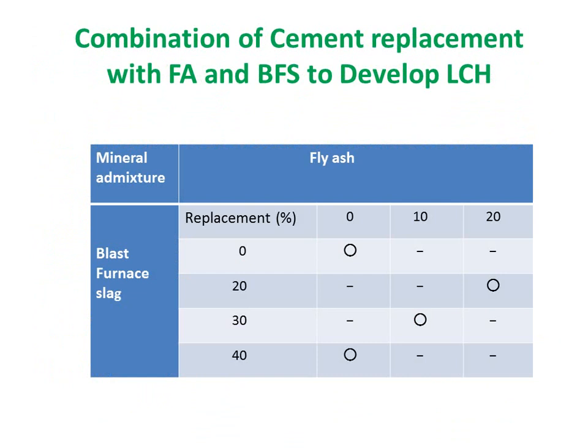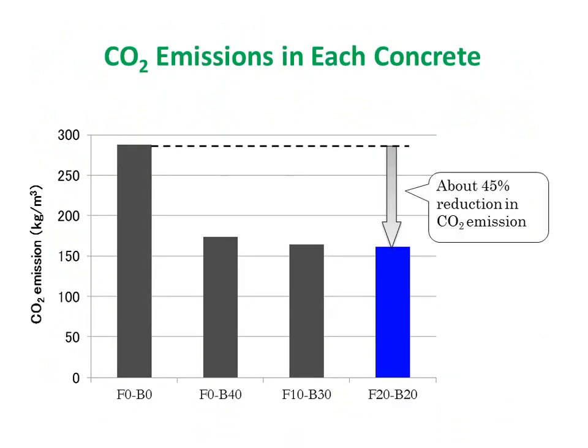This is the test cases in which we had to develop the low carbon high performance concrete. We utilized fly ash and blast furnace slag. For blast furnace slag, the cement replacement was 20%, 30%, 40%. And then here, this is the 10% fly ash replacement and 20% fly ash replacement. Then we found that the CO2 emission in each concrete is like that. This is the ordinary Portland cement. This is the F20-B20. So it means that almost a 45% reduction in carbon dioxide is achieved.